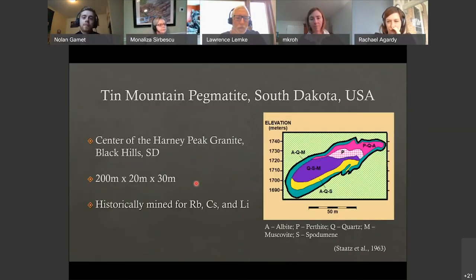The first pegmatite in the study was located in Tin Mountain in South Dakota. It is located in the center of the Proterozoic Harney Peak granite in the Black Hills of South Dakota. This inclined pipe-shaped pegmatite, as seen in this image on the right, is approximately 200 by 20 by 30 meters in extent, and this was historically mined for rubidium with alkali feldspar, cesium with pollucite, and then lithium within spodumene, which were found in the core and second intermediate zones, as seen in this picture by QSM and AQS.